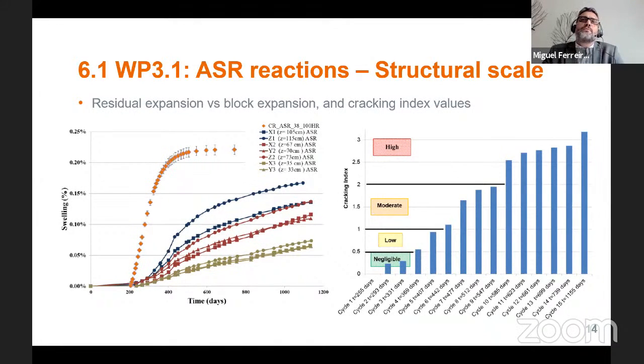So even though the swelling in both samples is activated by the high temperature, the 38 degrees, we notice that the swelling amplitude and the kinetics differ greatly if we look from the sample on the left to the curves on the right. Firstly, we noticed that in the core, in the lab, there's no latency time. That means that the swelling is initiated as soon as the samples are conserved at 38 degrees, whereas in the concrete block, it took some time before the reaction started.